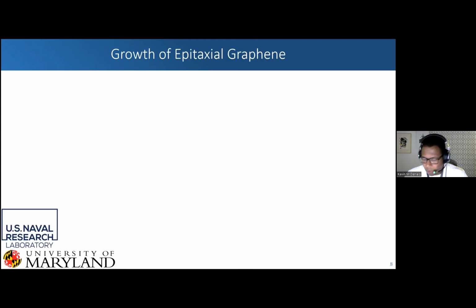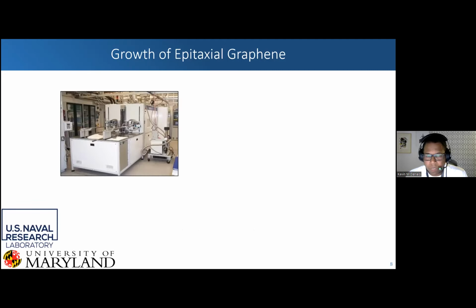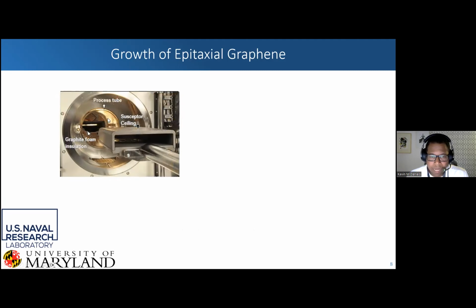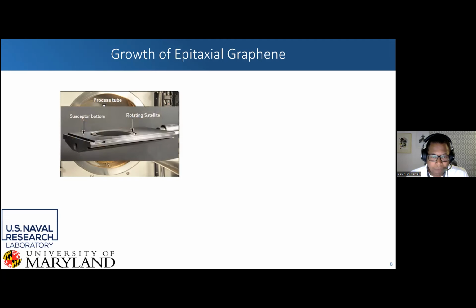And so, going back to the epitaxial graphene. When I was a postdoc at NRL from 2014 to 2017, this is the reactor I ran just about every single day. The chamber to the right is used for growing silicon carbide epi. The chamber to the left is for growing epitaxial graphene. And how that works is pretty much everything is made out of graphite. So we have our susceptor ceiling, which is made out of graphite. We have graphite foam insulation, which is, of course, a little bit more porous graphite foam. Inside, we have a susceptor bottom made of graphite, and then we have a rotating platter here.